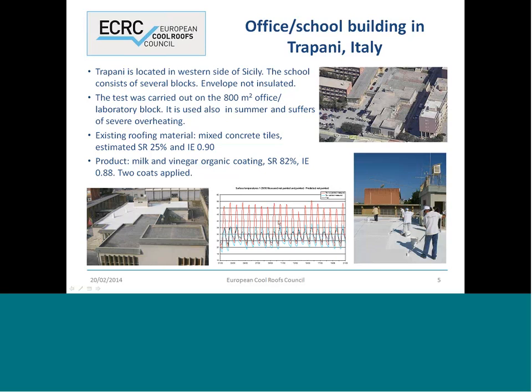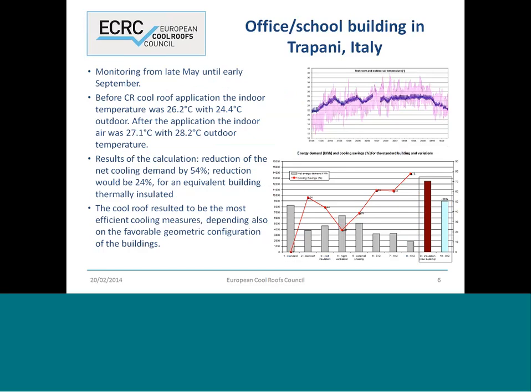And the graph in the middle shows the fluctuation of the air temperature in black, the surface temperature of the cool roof in blue, and the surface of the roof not treated during the month of August. The cool roof gets up to 4 or 5 degrees above the air temperature during peak time, while the untreated roof reaches values up to 25 degrees hotter than the air. The monitoring started in late May and lasted until early September.